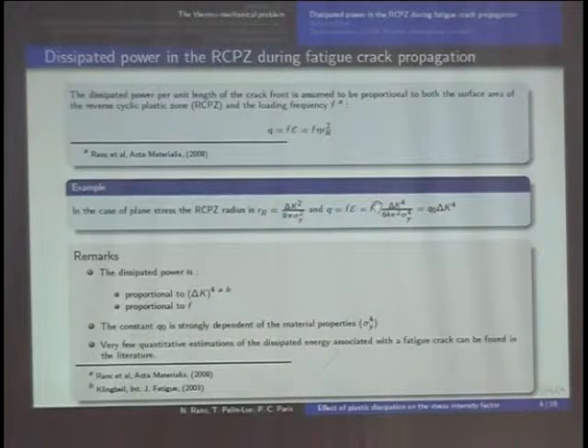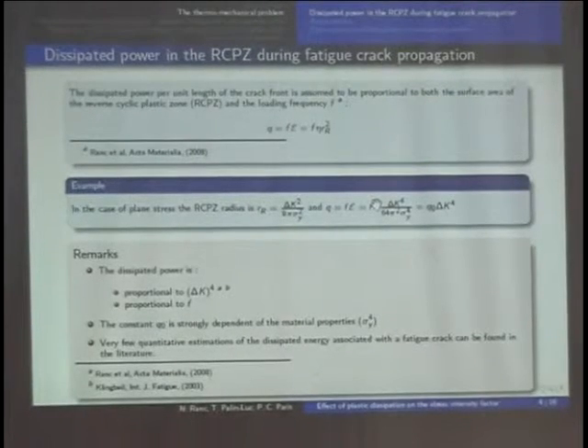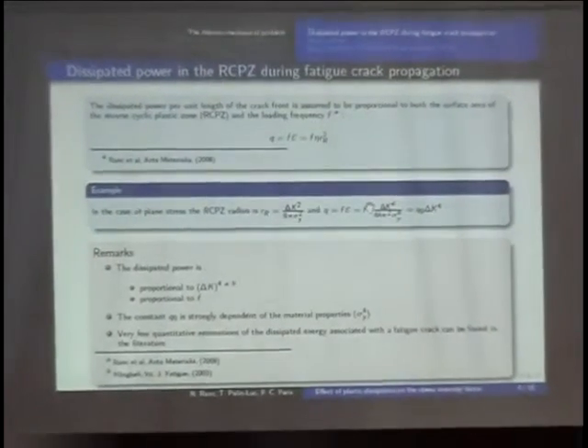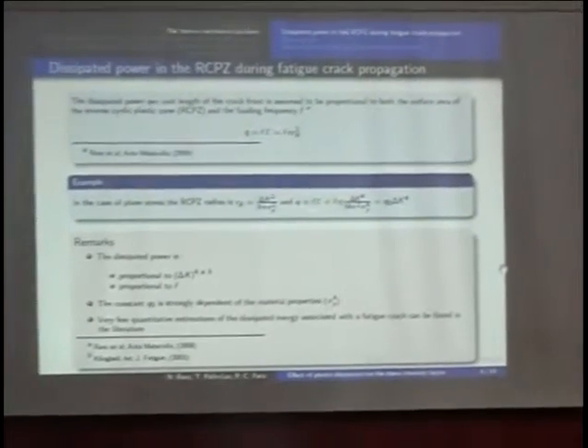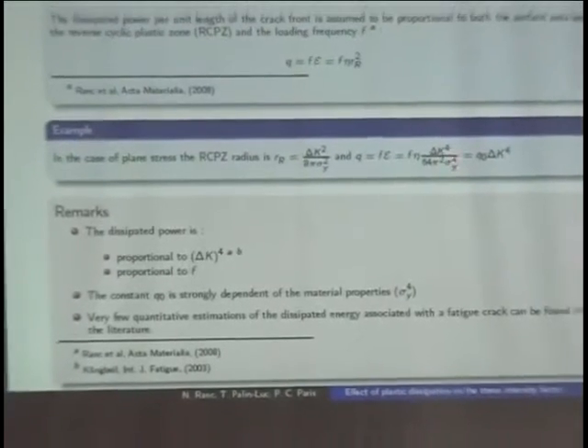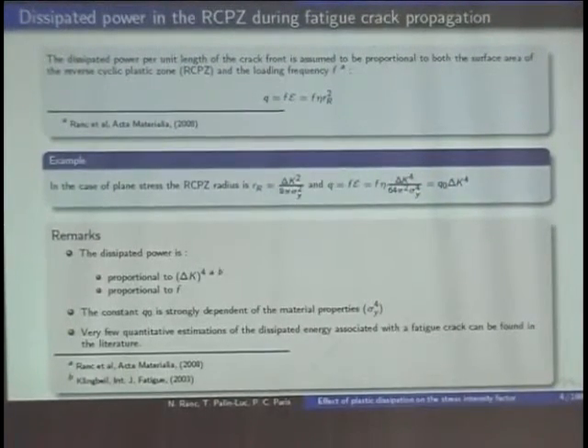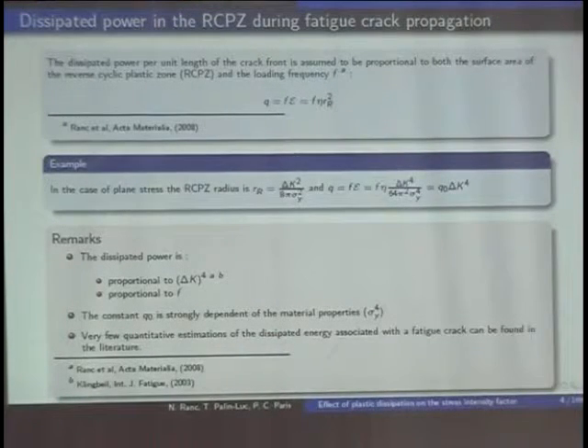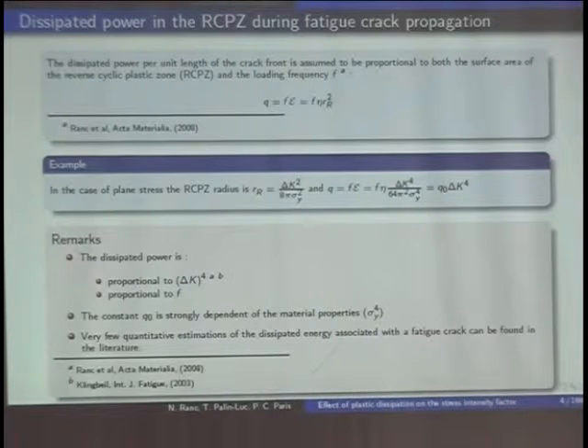I will come back at the end in the prospects, but the proportionality with the loading frequency is interesting for future works, I think. For instance, if you are in plane stress, but it's the same in plane strain conditions, you can compute the reverse cyclic plastic zone with a very simple approximation, and in this case, you can see that the heat source or the flux of the temperature is proportional to delta K to the power 4. It's important to note these two proportionalities, and also that Q0, this factor, is strongly dependent on the material properties, because you see that the yield stress appears here with the power 4. But in the literature, there are only few quantitative estimations of this dissipated energy. We will come back to it at the end of the presentation.